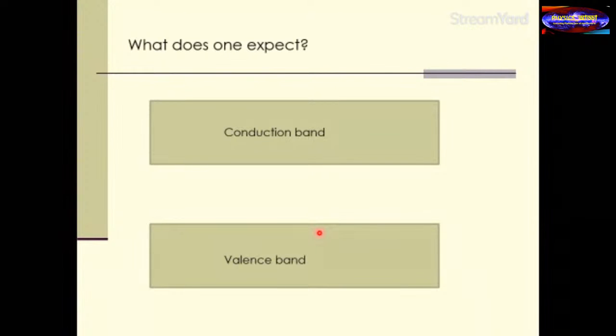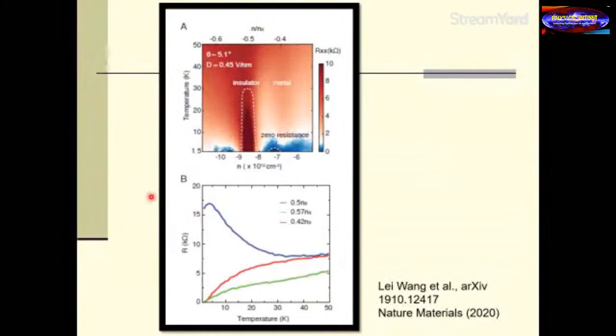So I see this in this class of materials. This was actually put into a phase diagram over here by the same group, and what they saw was, as a function of temperature as well as hole doping concentration, if they color coded the resistivity according to this bar chart over here, at low temperatures you're going to see states which are zero resistance, almost like a superconductor, but this hasn't been verified. And then you have essentially a metallic state which has very low resistivity or zero resistance, and then again an insulator, and then again back to metallic transport at quite low temperatures.